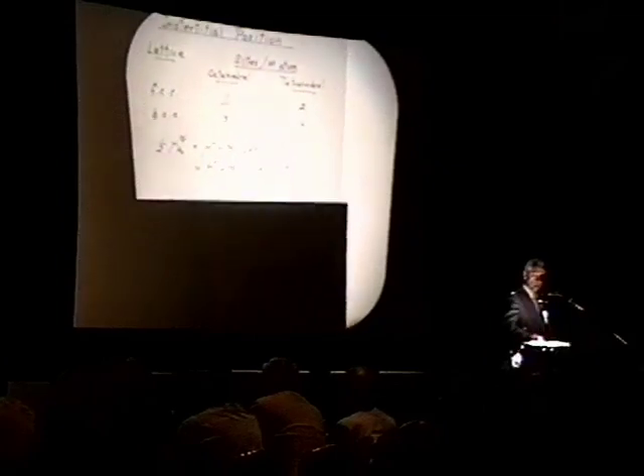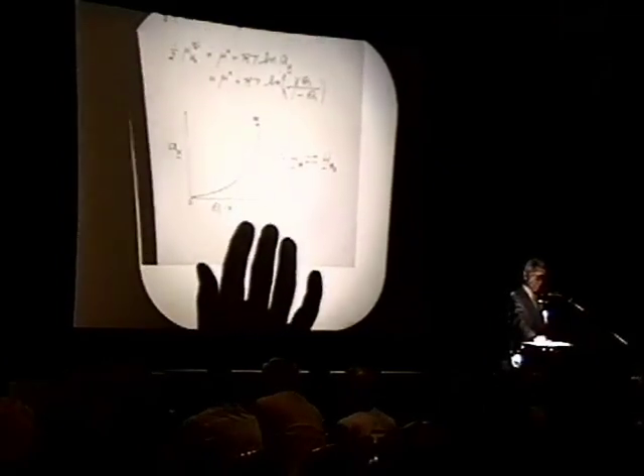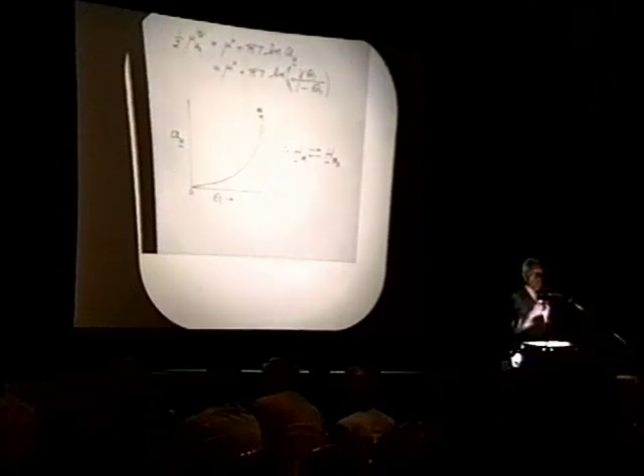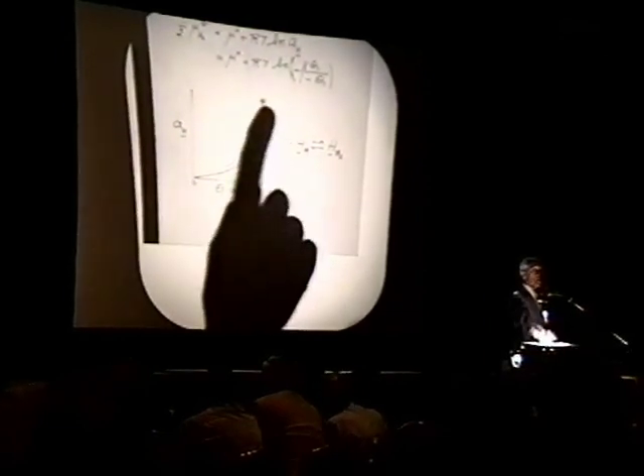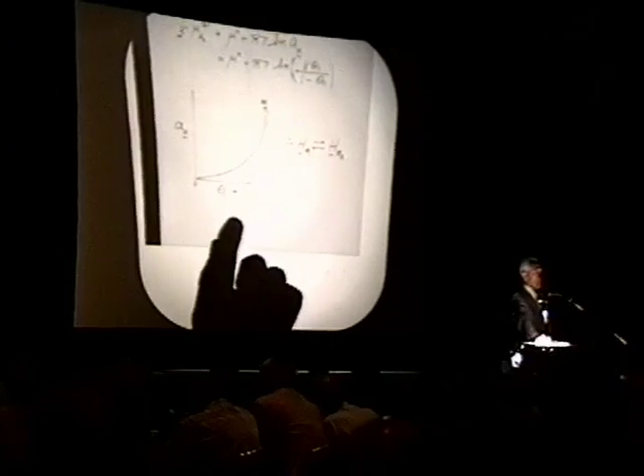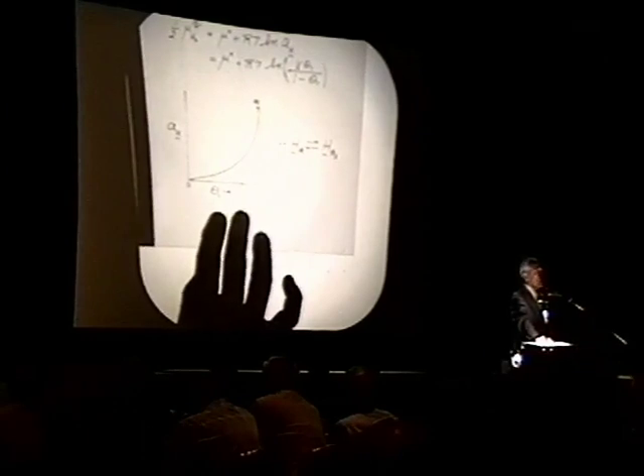The consequence of this is that as one increases the population in that category of interstitial sites, what I would call category 1, the lowest energy, which is the octahedral sites in the case of FCC palladium, as that approaches unity, the activity necessarily goes to infinity. So that means if you cannot apply sufficient external chemical potential of the gas to fill all those interstitial sites, in the case of hydrogen in palladium, the octahedral, what has to happen is it spills over into the next category, the higher energy category, which is tetrahedral in that particular case.